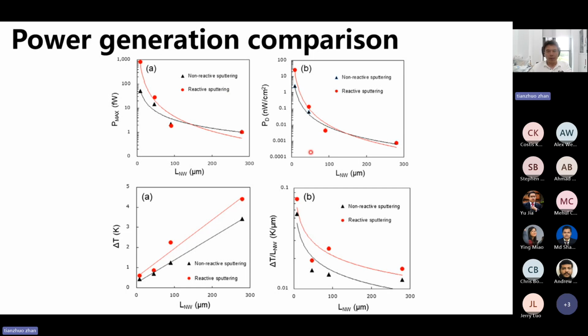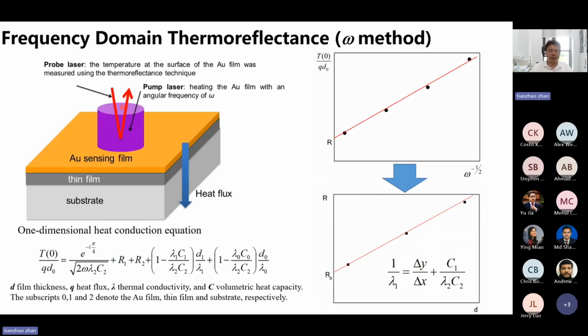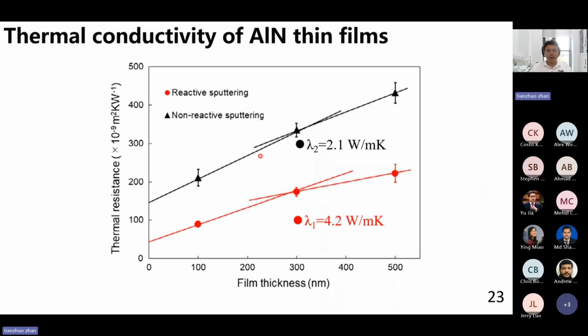And so we use the frequency domain thermoreflectance method to measure the thermal conductivity of the aluminum nitride thin film, and we found the aluminum nitride thin film deposited using the reactive sputtering method has a higher thermal conductivity than the non-reactive sputtering method. But both of these two samples have significantly lower thermal conductivity than the bulk aluminum nitride.